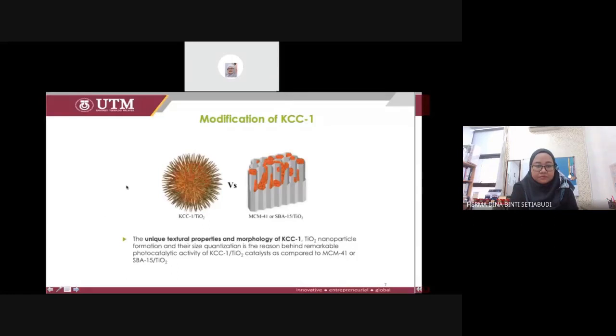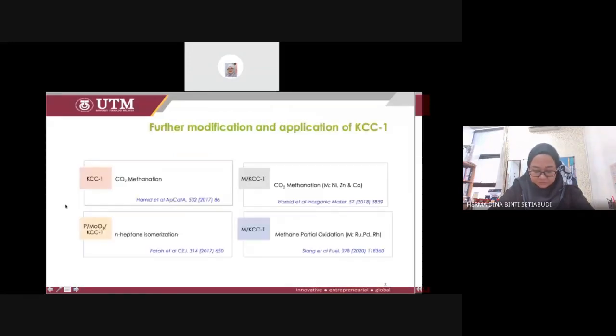Okay, the professor and co-workers also tried to disperse the TiO2 on the KCC1, as you can see here in the orange color. They compared it with the TiO2 dispersed on the MCM41 or SBA15. Okay, you can see this is small particle dispersion, and then this is quite agglomerated because of the structure of the support. Then the unique textural properties and morphology of KCC1 with the TiO2 nanoparticles, and also their size quantization, you can see the size of the TiO2, become the reason behind the remarkable photocatalytic activity of the KCC1 as compared to MCM or SBA15 with the TiO2. Okay, that's about the previous results.